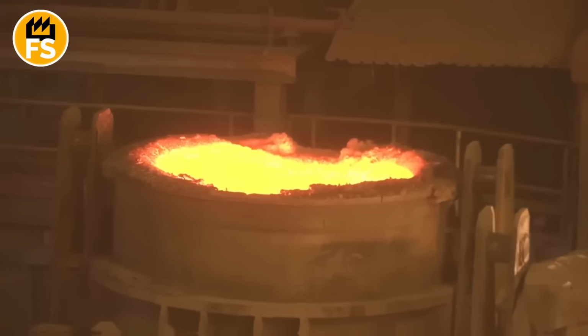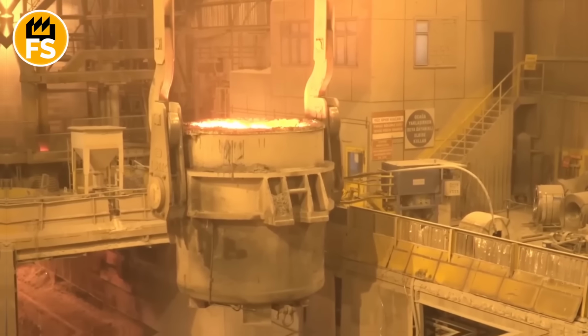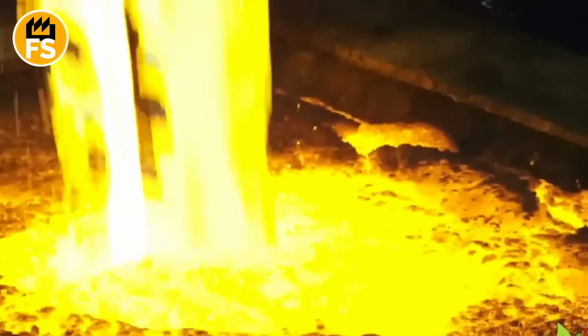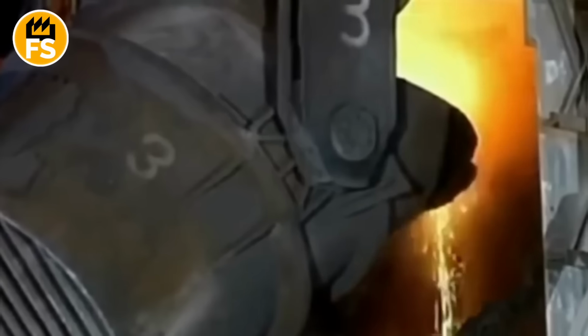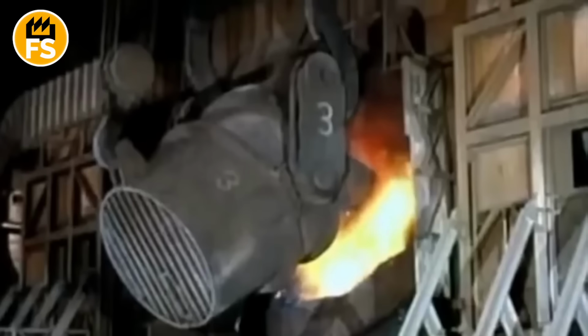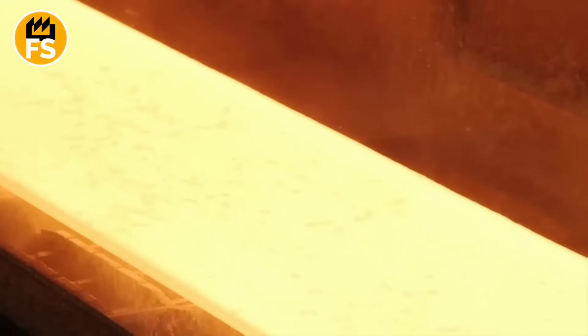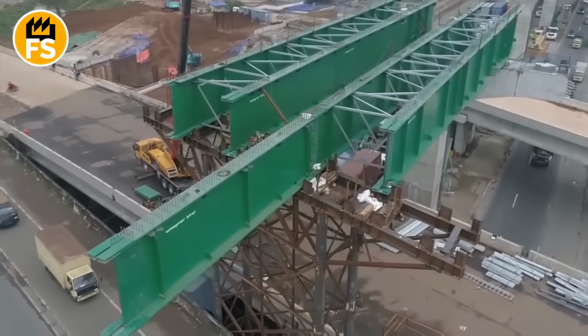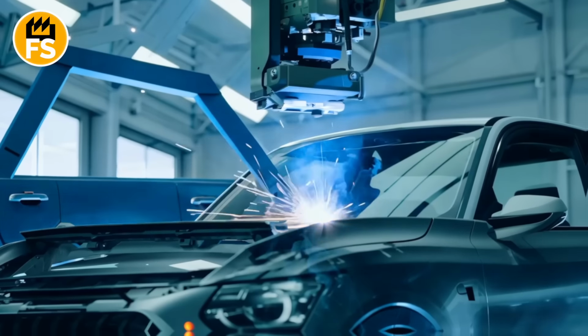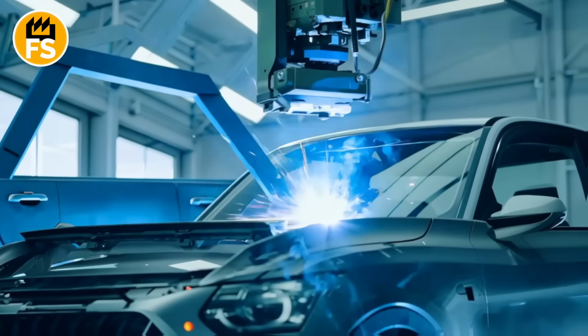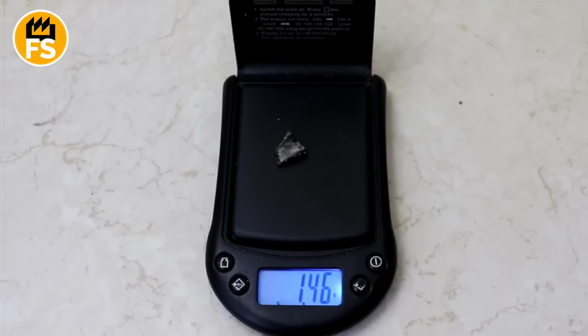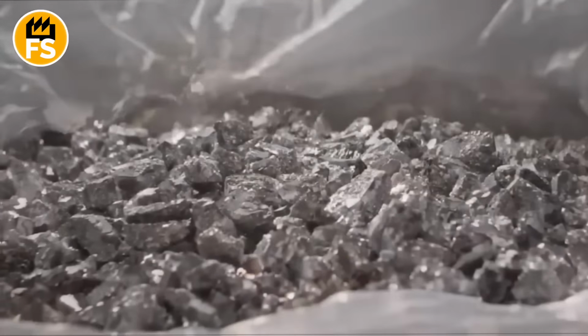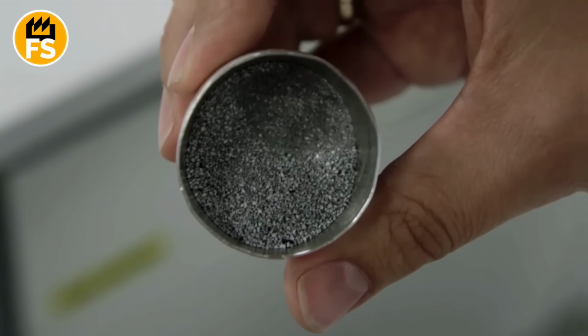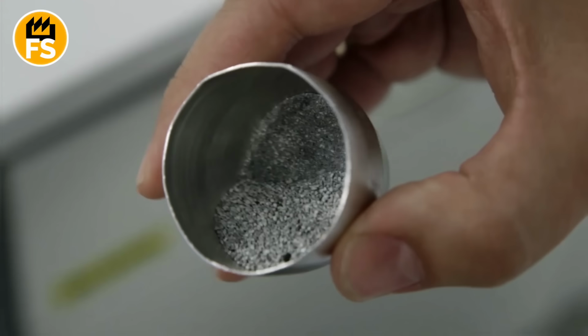The main value of ferrovanadium lies in its predictable behavior in molten steel. It dissolves quickly, is barely lost during melting, and allows precise control over microalloying. That's exactly why ferrovanadium became the standard form of vanadium supply for producing high-strength steels, from building structures to automotive components and armored products. The key feature of vanadium is that it works in microdoses. To get a noticeable effect, just tenths or even hundredths of a percent are enough.